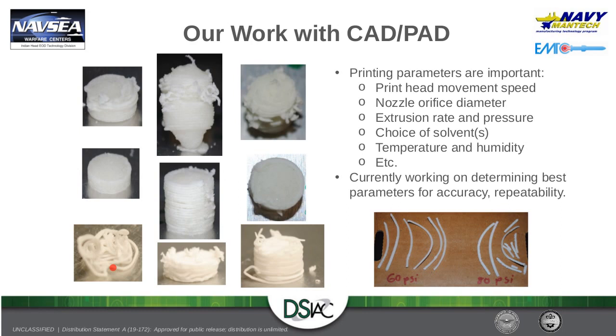And these parameters are not limited to the actual print head movement speed, which is the actual speed that the head moves in X, Y, and Z. If the print head is too fast, that can make a very small, thin bead that doesn't really stick to anything or cause little skips as you're printing. If you move the head too slowly, you can spurt out way too much material in a single place and you're left with a blob.